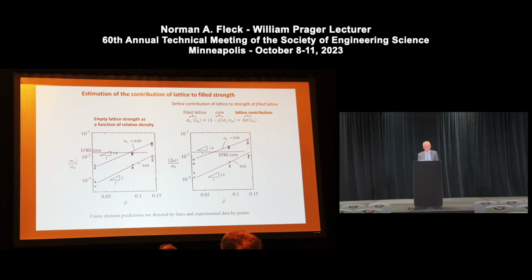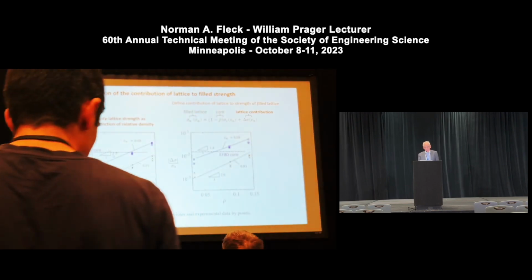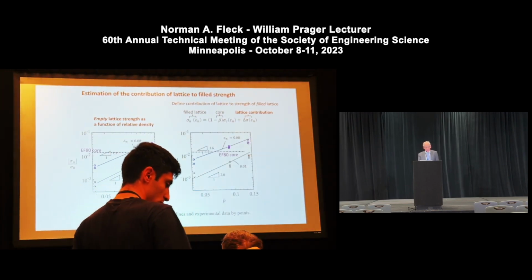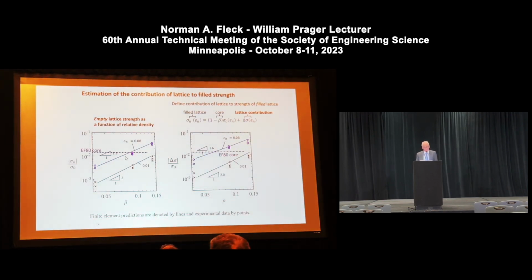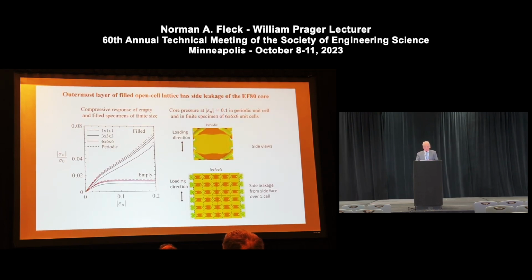And you can see in both cases the slope is well above 1. 1 would be linear. It's closer to 2 here and 1.6 here for the filled lattice. A slope of 2 would be consistent with bending type behavior. And that hardly changes when we add the incompressible core. So for the case of these three-dimensional lattices, the take-home message is that the fundamental mode remains bending, but in a mode which is not constant volume. So you get some strengthening, but the important feature is the much more stable behavior. Okay.